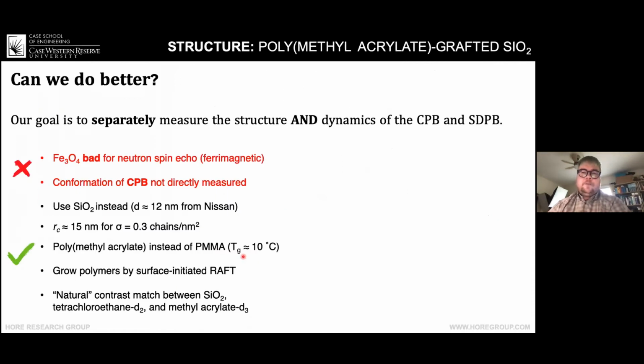But the question is, can we do better than this? This is the more recent study, because that previous example was iron oxide nanoparticles, which are bad for spin echo. Spin echo uses very, very strong magnets, so we can't have particles that have a magnetic moment. What I just showed you, we never actually measured the conformation of the chains in the stretched region. We assumed it was a uniform density shell of polymer. So can we address that? What we did instead was use silica that's 12 nanometers in diameter from Nissan.